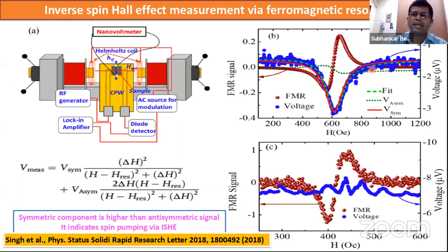So we did that, and here we just show a reference sample of the single layer, and we see no spin pumping. So it clearly shows that with bismuth selenide you get a beautiful spin pumping voltage. Then obviously that signal you can disentangle into the symmetric and anti-symmetric component, and that's basically right here.